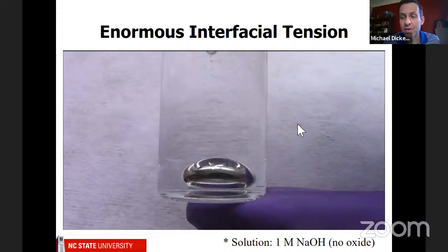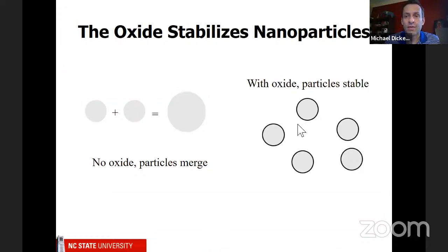However, if you do this experiment in conditions where the oxide can't form, then if there's no oxide, two particles merge together and form a bigger particle. But if you have the oxide layer, that can help stabilize it. And so we and other people have used this to make very small particles.